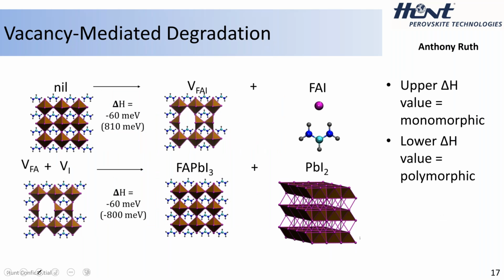So one of the ways is that when we've kind of covered here with XRD, the XRD approach is vacancy-mediated degradation. So again, Nil, that's the initial perovskite, that's the cube here, or the supercell we're using for our DFT calculation. And we show what happens if we form these same Schottky defects. We remove an FA and an I separately. We represent them as one here combined, but we have now in this structure an FA and an I vacancy. So in the polymorphic degradation, you actually have an exothermic reaction, very small, but there's a little bit of energy release there, negative 60 meV for the delta H. But if it's monomorphic, it's actually quite positive, 810 meV.